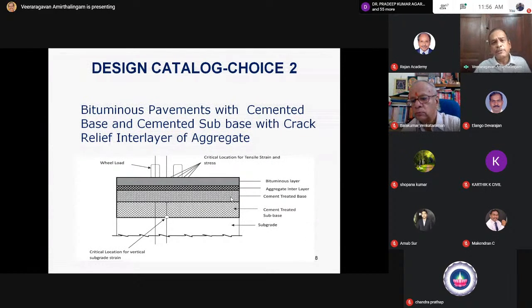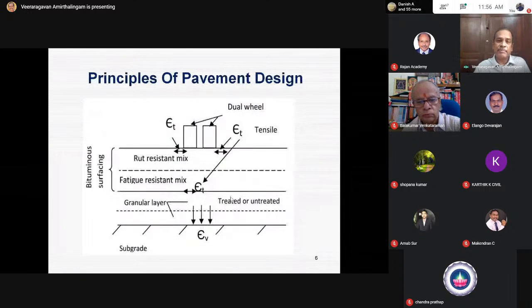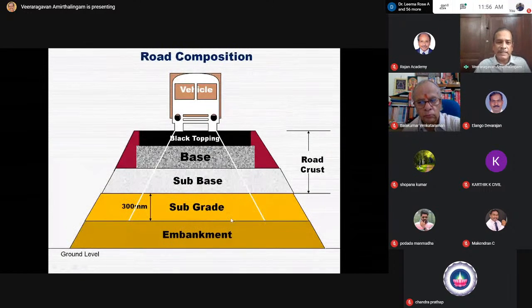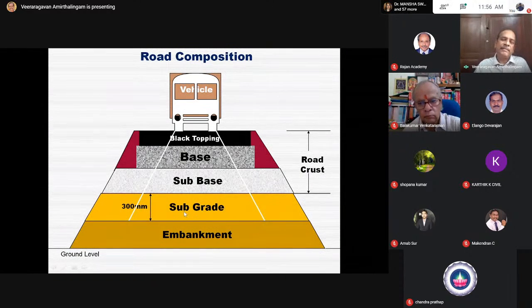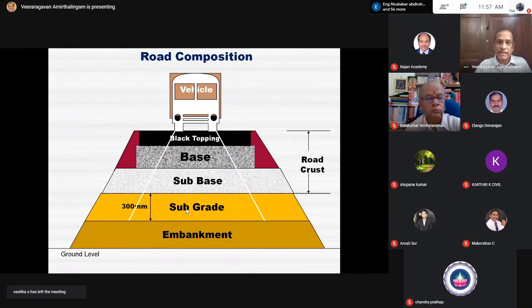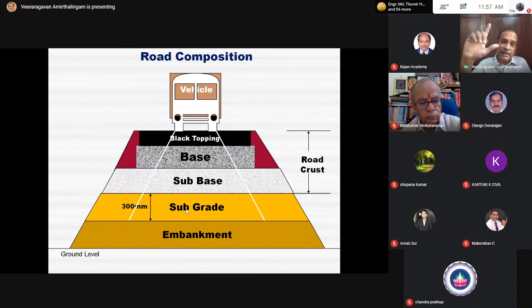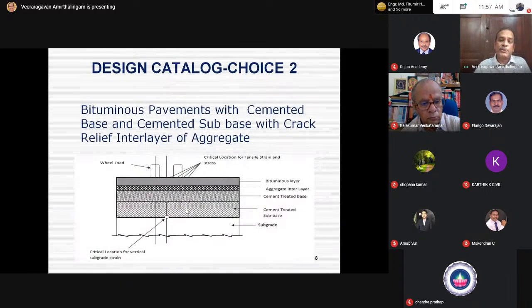Can I stabilize subgrade also? Yes. The issue that you should consider at this point of time is that the stresses coming at the bottom layers are much, much lower. If you want to improve the property of subgrade, the percentage of cement, I just give an example, cement, it can be any other stabilizer, maybe 1%, 1.5%. By improving the subgrade strength, the thickness of the pavement can be brought down significantly. So in this case, when you have a cement-treated base, cement-treated subbase, you can reduce the thickness significantly.